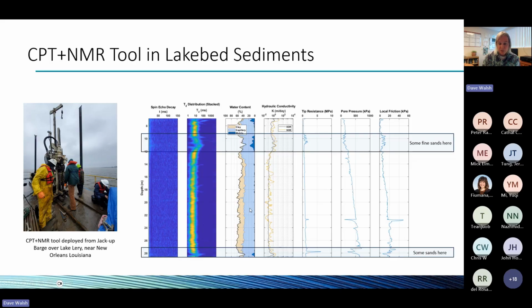And you can see some interesting differences, like where you've got a little bit more sand mixed with silt, you have a lower porosity. That's because the sediment is less well sorted, right? And that leads to a lower porosity. And you can also get quantified estimates of hydraulic conductivity.